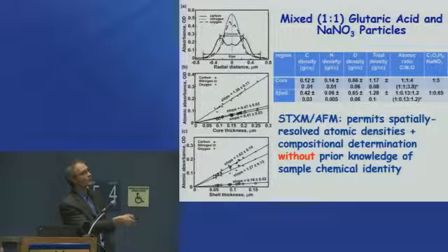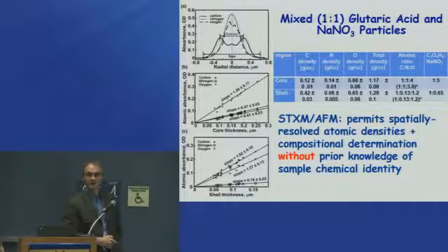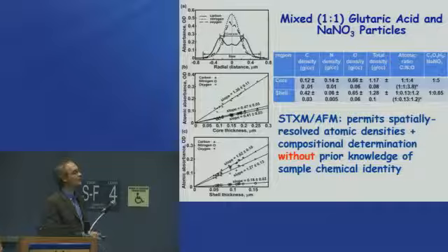So in the core, we have the ratio of 1 to 5 between organic to inorganic, and in the shell, we have approximately 1 to 0.65. And this is how it varies as a function of size.